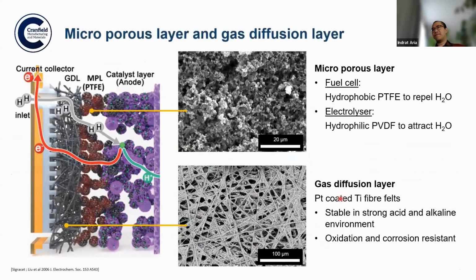So what are these materials? For the microporous layer, this is the interface between the gas diffusion layer and the catalyst. These are basically fluorinated polymer. It can be hydrophobic for fuel cell or hydrophilic for electrolyzer. The reason we want hydrophobic fluorinated polymer is that we want to repel the water. Water is the byproduct or the product of fuel cell, so we want it to be expelled as quickly as possible. We don't want that to create a bottleneck.